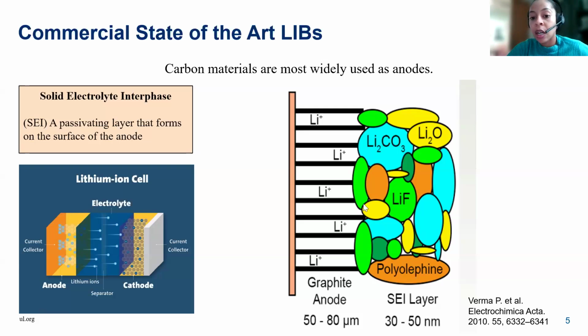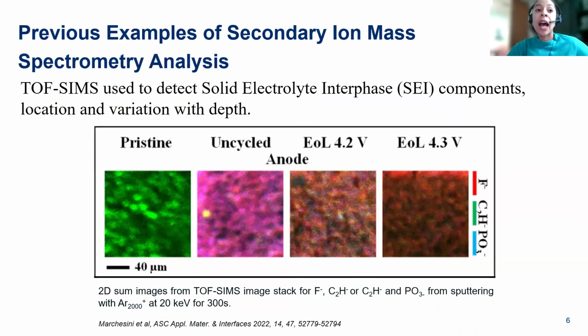So here we have a little cartoon of the lithium-ion battery and the SEI layer. We have the orange, which is the copper current collector. We have the black lines that act as the layers of the graphite, and we have some of the major components of the solid electrolyte interface, or the SEI, for example, Li2O and LiF. We have actually at NPL shown that there are different types of secondary ion mass spectrometry that can be used to study this layer.